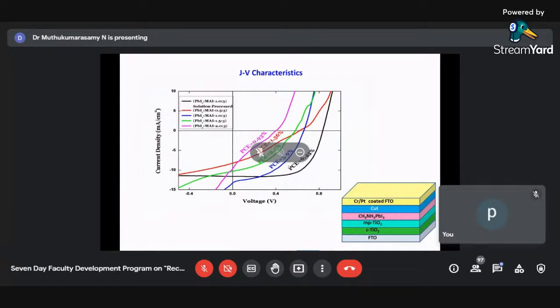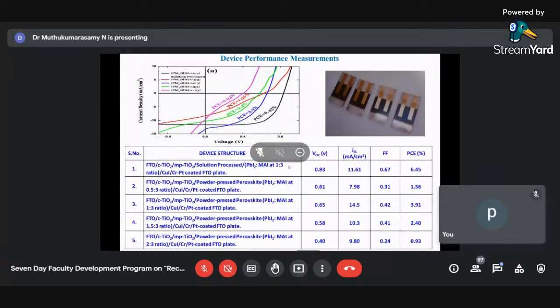Whereas when we went for a solution processing technique, we got 6.45%, because in the powder press technique, there was no good connectivity between the perovskite layer and the electron transport layer, because there were so many pores associated, and the linking was not there, or we can say surface associated problems are there. So these are the cells which we fabricated. We got an efficiency of nearly 4% and 6.45%.